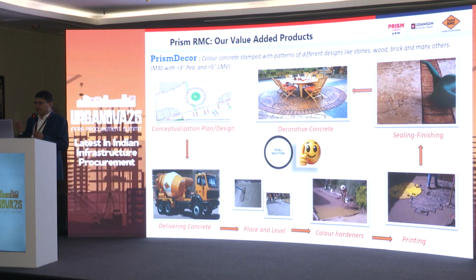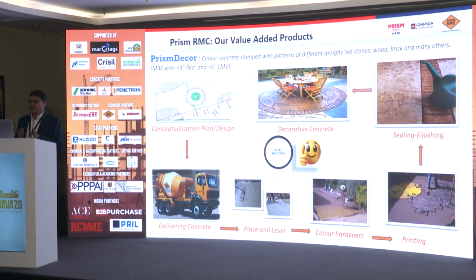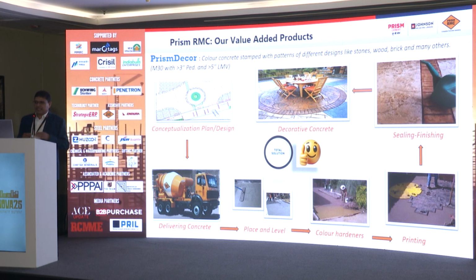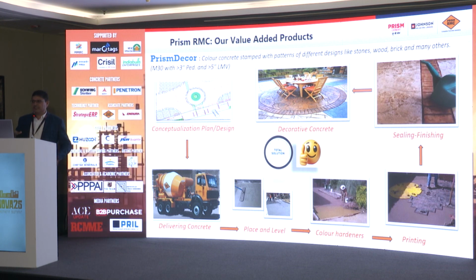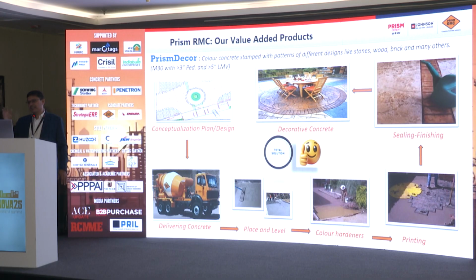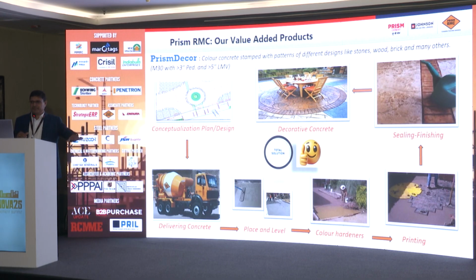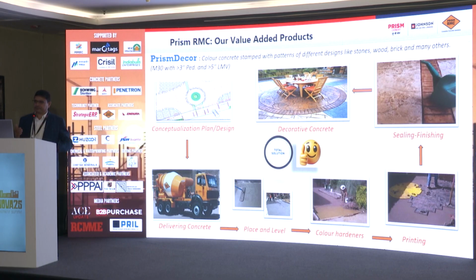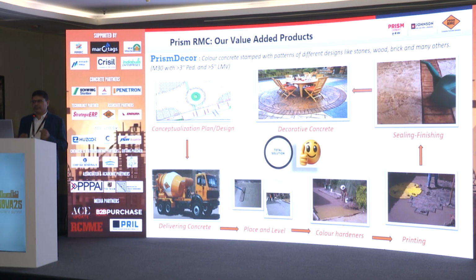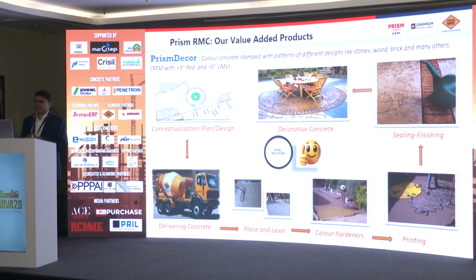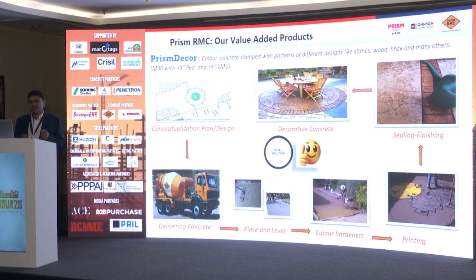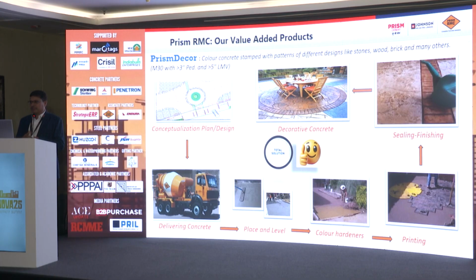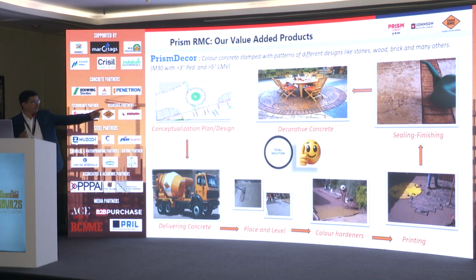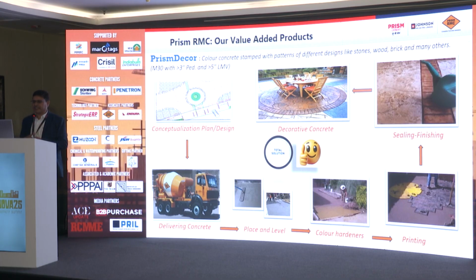After that, the releasing agent is applied over the surface. Then the concrete is printed using a rubber mold, so as per the required designs, the surface is printed. After that, the joints are cut within a time of 48 hours. Then the surface is washed using jet water, and once the surface is washed, we get a picture like that.